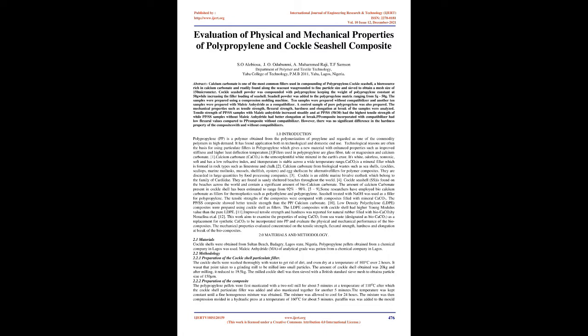10 samples were prepared without compatibilizer and another 10 samples were prepared with maleic anhydride as a compatibilizer. A control sample of pure polypropylene was also prepared. The mechanical properties such as tensile strength, flexural strength, hardness, and elongation at break of the samples were analyzed.